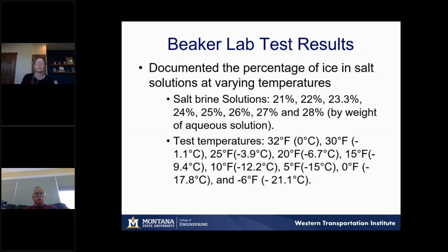A large part of this project involved lab testing. So first I'll talk about the beaker test. The goal was to document the percent of ice that formed in different salt solutions. So we had salt solutions that varied from 21 to 28% by weight of aqueous solution or liquid content. And we tested this at various temperatures. So there were 9 different temperatures from 32 degrees all the way down to -6 degrees. And this was all done on MSU's campus and the cold labs.